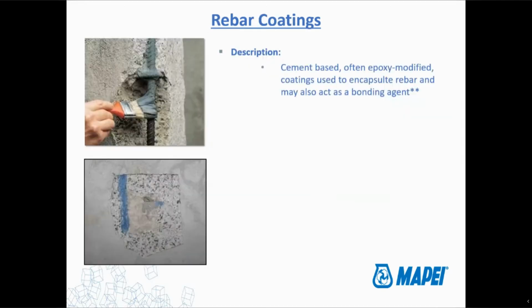There's also the coatings that I mentioned. So there's cement-based, there's also epoxy-based coatings. The idea with the coatings is the same as the anode, really. You're just preventing the anode-cathode cell from forming by putting a coating around the steel. They work really well just so long as you completely coat the steel. It's the same as epoxy coated bars. If you don't completely coat it front and back on all sides and every little nook and cranny, it's not going to work.